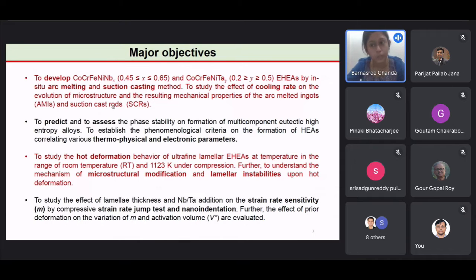That is, to develop the eutectic high entropy alloys by suction casting and arc melting, to predict and assess the formation of phases and phase stability by thermo-physical and electronic parameters, to study the hot deformation behavior, and further to study the mechanism of microstructural modification and lamellar instability upon hot deformation, to study the effect of lamellar thickness and alloy addition on the strain rate sensitivity by strain rate jump test and nano indentation, and further to study the deformation behavior.